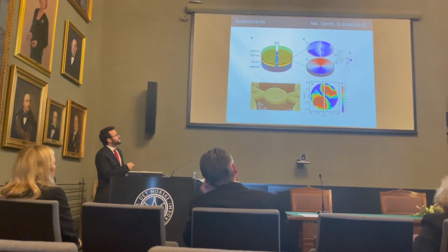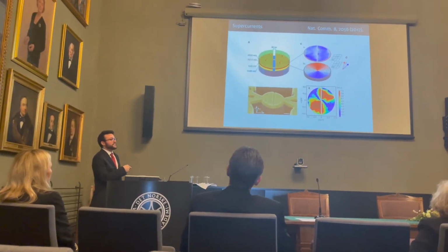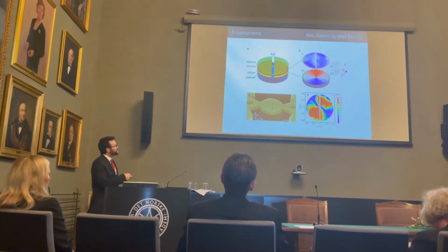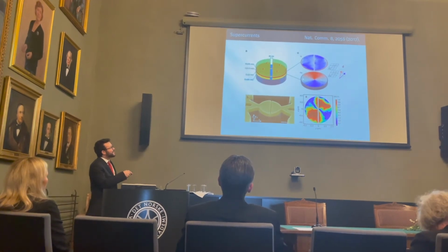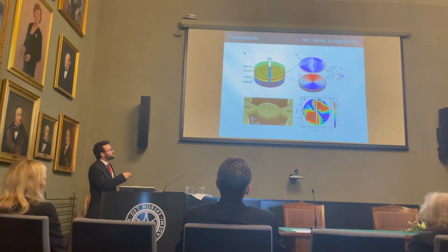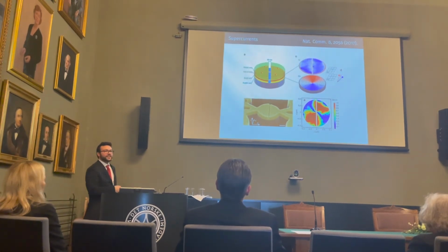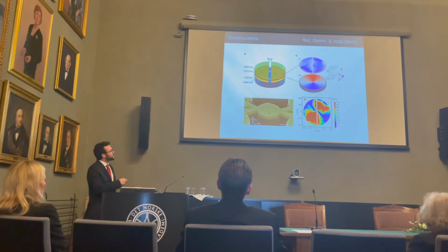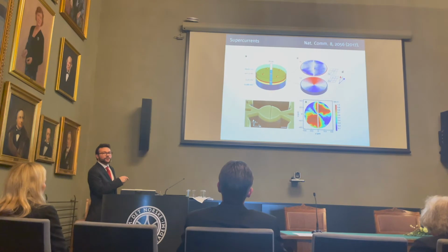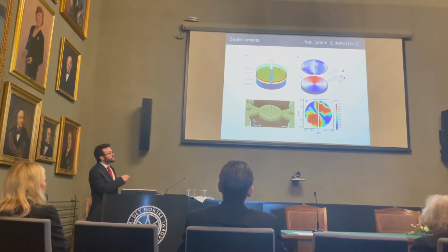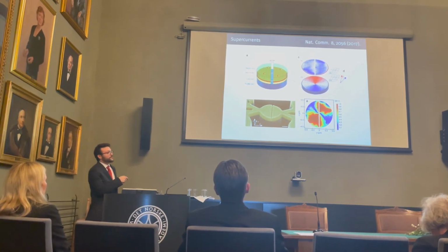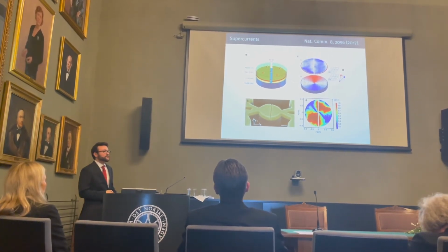They made a disk of cobalt, which is a strong ferromagnet, and this disk geometry, here's a real picture of it, the disk geometry makes the magnetic field point around in a circle inside the magnet, a so-called vortex configuration. Then on top of this cobalt disk, they added a thin layer of copper, which is a normal metal, of nickel, which is another magnetic layer pointing in a different direction, and then on top is a thicker layer of niobium, which is a good conventional superconductor.